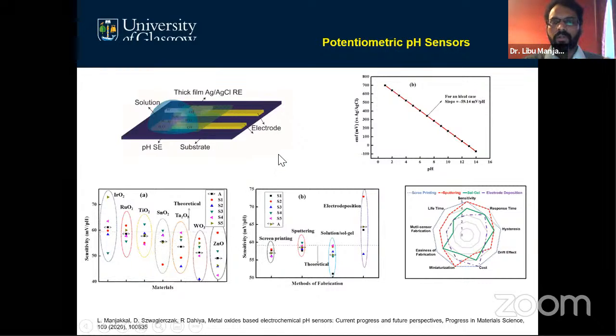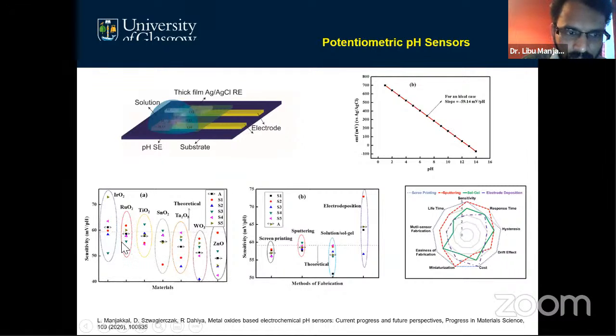For example, if you are a master's degree student or a PhD student who wants to develop a new pH sensor, you can check all these types of material. For example, iridium oxide shows a super Nernst response. It depends on how many electrons are involved in this electrochemical reaction. There are iridium oxide and then ruthenium oxide. I found that from iridium oxide, ruthenium oxide, Ta2O5, you can see here this central bar, the theoretical value 59.14 millivolt. Ruthenium shows almost near to that ideal Nernst response on average.